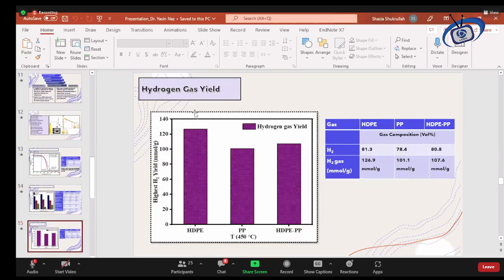Then the gases we get during this process, we analyzed to check their composition, and we found that this gas consists of 81.3% hydrogen when HDPE was used as a feedstock, and 78.4% hydrogen when PP was used as a feedstock. And this figure slightly improved to 80.8% when we used a mixture of HDPE and PP. It shows that the hydrogen content was almost similar in all three cases. However, HDPE shows a slightly higher hydrogen content as compared to pure PP and its mixture with HDPE.